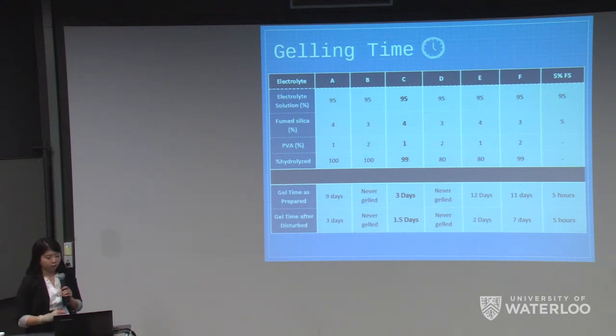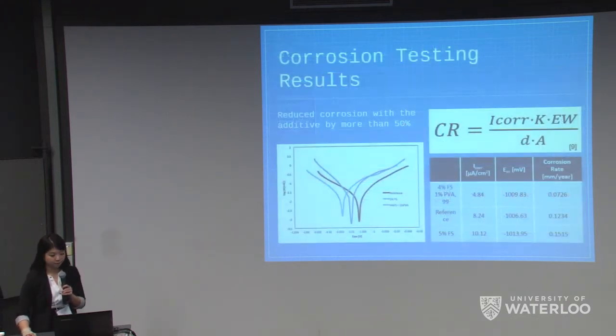This would mean that looking for a gel with results between 1 to 6 days gelling time in the lab would correspond to what we were looking for in industry requirements. And the best results that we were able to get would be our Electrolyte C, which gave us 3 days, and then the second gelling time of 1.5 days. And the composition of this was 4% fumed silica and 1% of 99% hydrolyzed PVA.